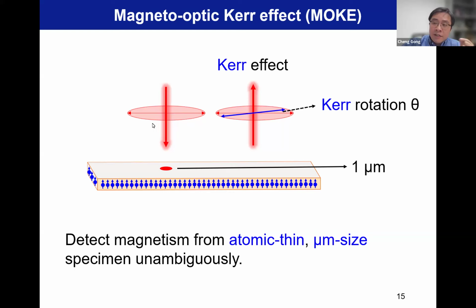You know, the polarization of this light will have a rotation. And then by keeping track of this Kerr rotation, you can keep track of the magnetic signal as a dependence, for example, on the thickness of the sample, on the temperature, on the magnetic field. So if you consider the other way, this linearly polarized light is the superposition of left and right circularly polarized light.